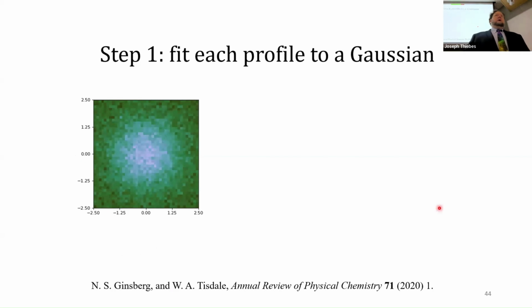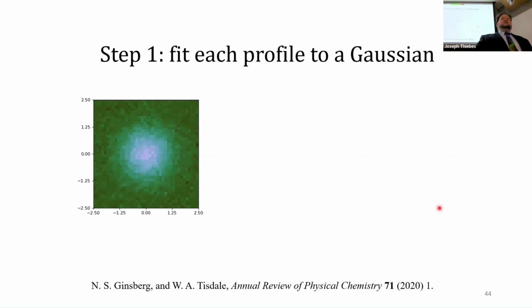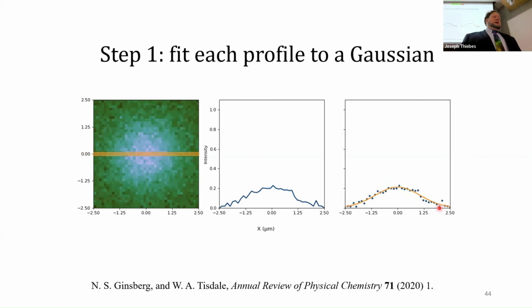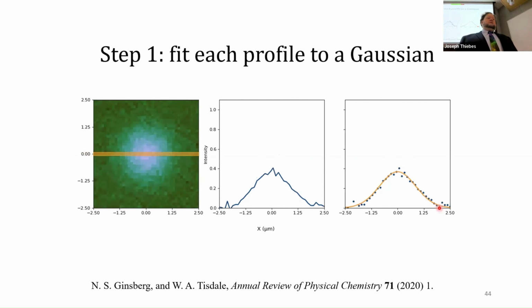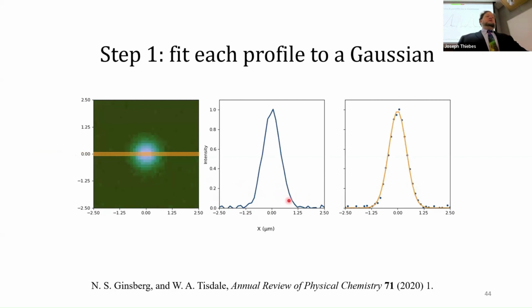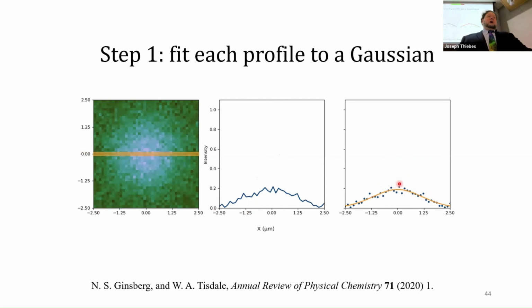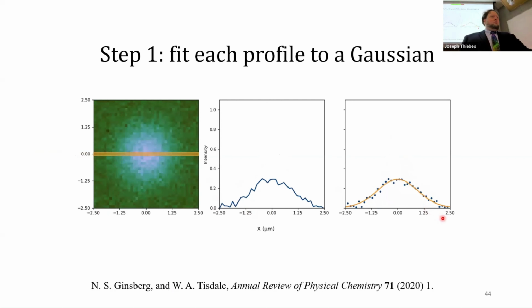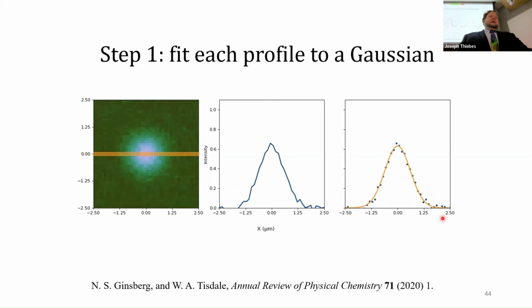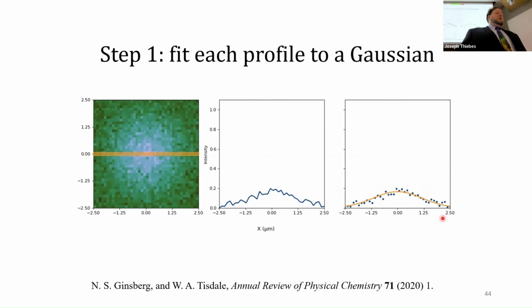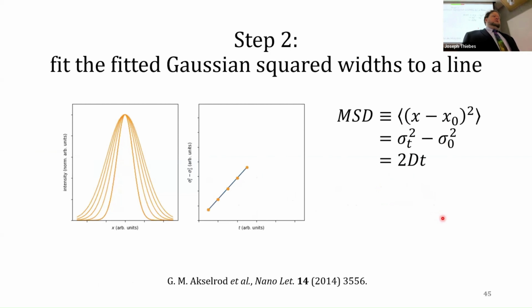So in calculating the diffusion coefficient, the first step is to fit each profile at each time point to a Gaussian function, either taking a slice or doing an integration in one dimension. And then we fit those. You see this blue line is showing the data itself, represented also by these blue dots, and then the gold line is the fit to the data. Then we get the width of that Gaussian at each of those times, and the square width scales linearly with regular diffusion. And that's shown here. As the population widens, and we're normalizing the height at each time step, the square of the width goes up linearly, and that's proportional to the diffusion coefficient. So that's how we measure diffusion.